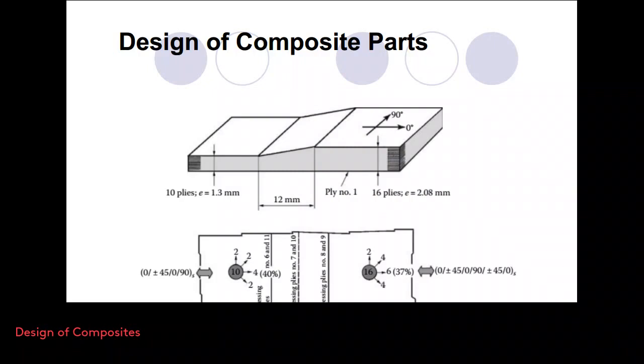In that case, what you do is like this. In every 6 millimeters you decrease 2 plies generally. Again, I'm saying generally because you cannot exactly say that this is a rule of thumb. So you made the calculation and you see that you need a 16 ply laminate with 2 plies in the y direction or 90 degrees, 4 plies at positive 45, 6 plies at 0 degrees, and 4 plies at negative 45 degrees. So we have this configuration: basically 0, plus minus 45, 0, 90, and plus minus 45, and then 0.